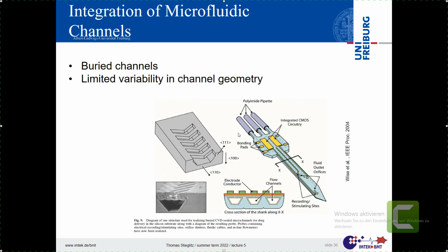And for the experts of you from the MEMS side, here the crystal orientations of the wafer give us the characteristic angle of wet etching if we use KOH, for example, and that chevron pattern. That's silicon. And if you do then, after that, a thermal oxidation of that, that means you grow silicon dioxide by adding oxygen and a bit of water vapor, and by that you would change the surface and all the edges here from pure silicon into silicon dioxide.